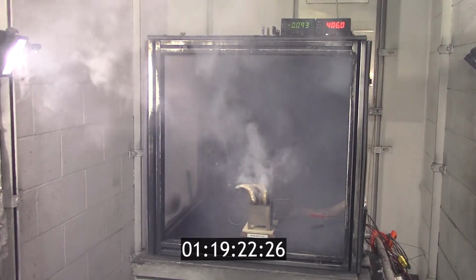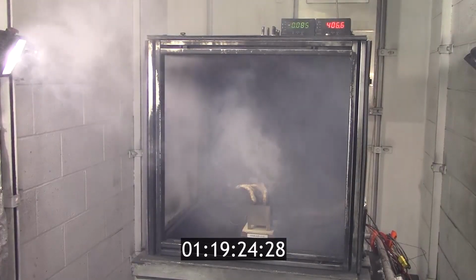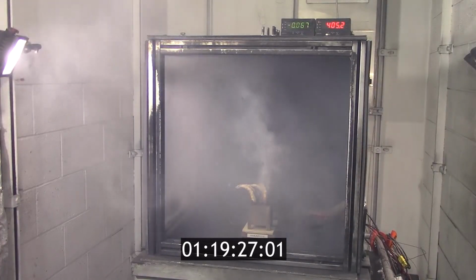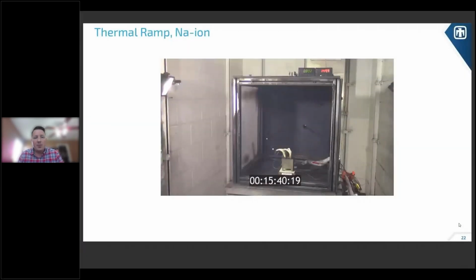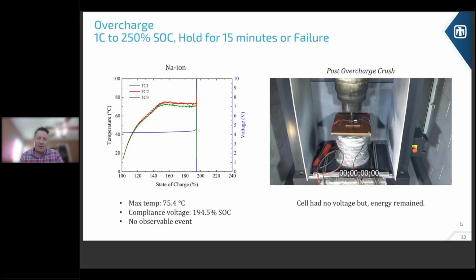All right, we move on. So that wasn't a distinct thermal runaway in terms of sparks and fire. Although if you notice the temperature above the box, we did increase from 300 degrees Celsius to 400 degrees Celsius quite rapidly. And so depending on who you ask, we do term that a thermal runaway. So again, it wasn't in terms of fire, but we did get a rapid increase in temperature.